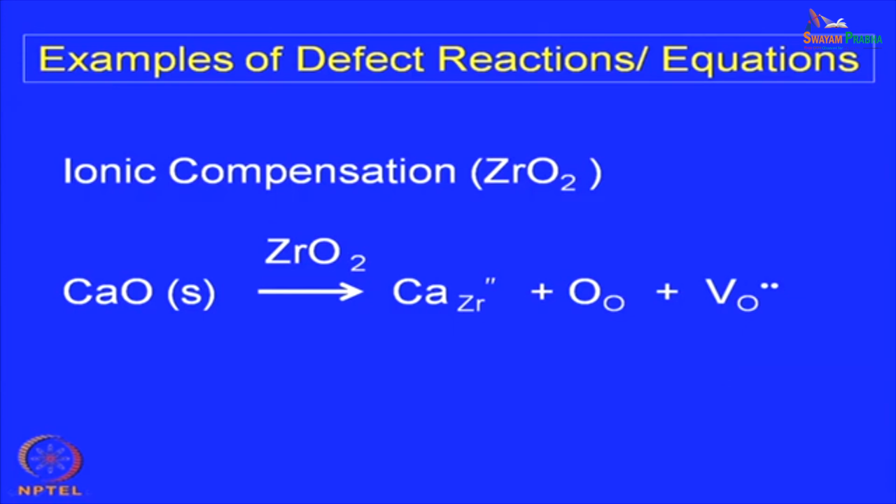Fortunately, in all oxides it can happen, because oxygen is available in the atmosphere and at slightly elevated temperature all these reactions can take place. There is a gas solid reaction. So, oxygen can exchange between the solid and the environment. It can go in or it can go out quite easily, because oxygen is available in the atmosphere, and the same oxygen is also available within the solid. So, if the kinetics is favorable, oxygen can exchange between the atmosphere and the solid. That is what happens.